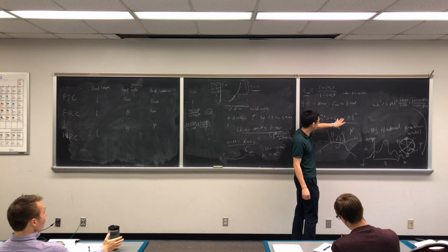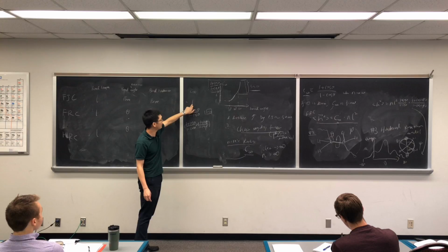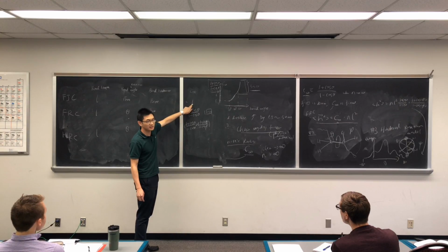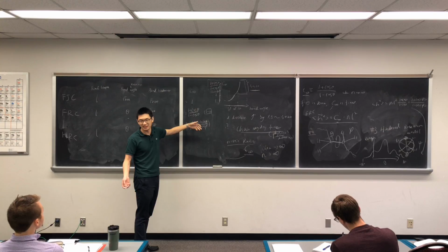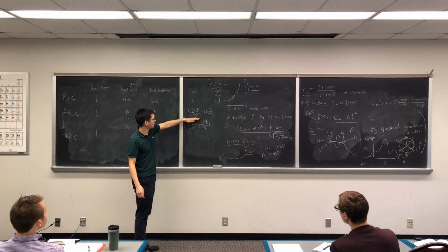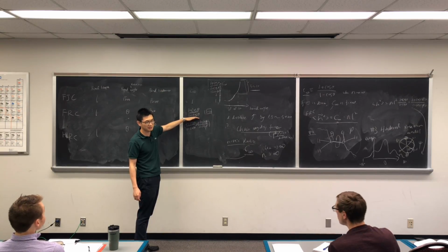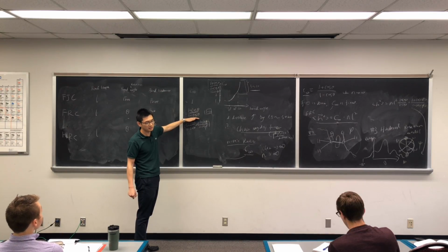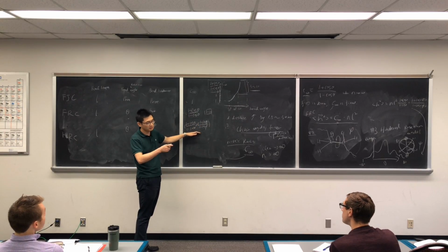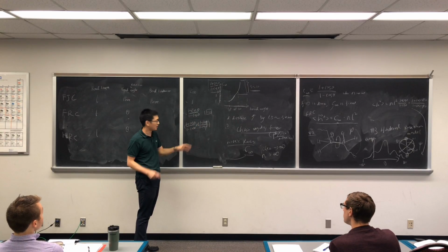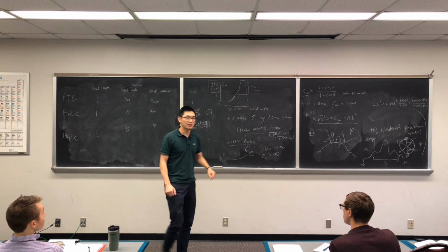So basically I write it here: characteristic ratio will be equal to 1 if it's NL square, right? Because effectively that would be 1. Characteristic ratio would be (1 plus cosine theta) over (1 minus cosine theta) if you consider the angle. And in the last case, if we consider even the hindrance angle, then there's one more restriction here, and that's being reflected.